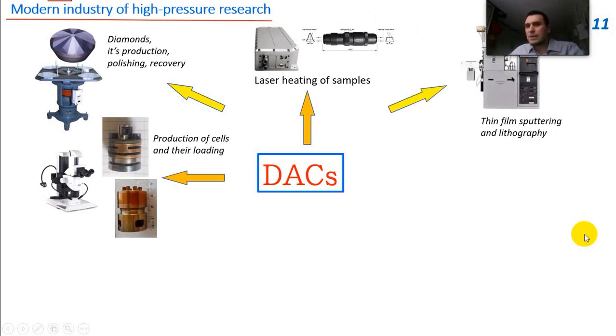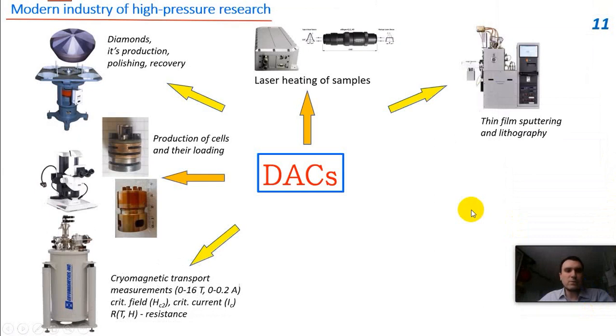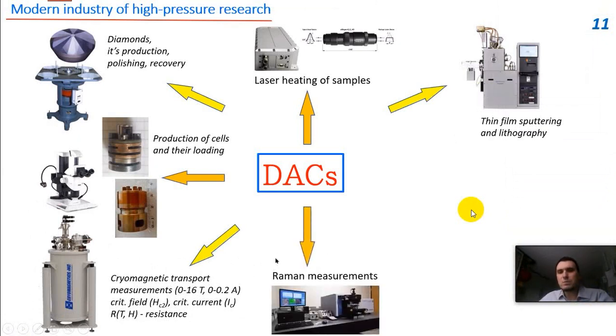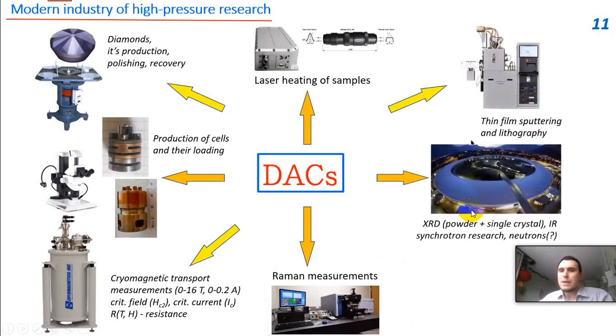Thin film sputtering and lithography is also necessary. And for cryomagnetic transport measurements, we ask the people from LPI to do these measurements, because they are really professionals in such a field. And the Raman measurements can be done in Skoltech. In the Red Building, we have quite a good instrument. It's a Horiba, and I think it's good enough to work with any pressure up to several million atmospheres.